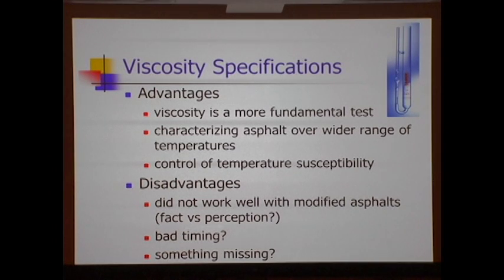Viscosity specifications, it's even like with the pen test or the penetration specification, there are advantages and disadvantages. Obviously, viscosity is a more fundamental test. The numbers actually mean something compared to how far a sewing machine needle pokes into a small sample of asphalt. As I said, we're characterizing asphalt over a wider range of temperatures, and thus we can control the temperature susceptibility of the asphalt, which is a very important thing to do. But there were some disadvantages, or at least one.